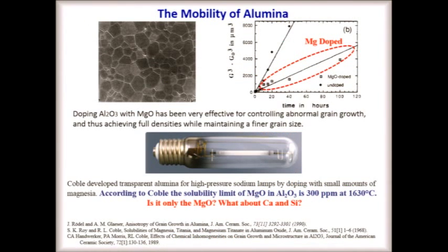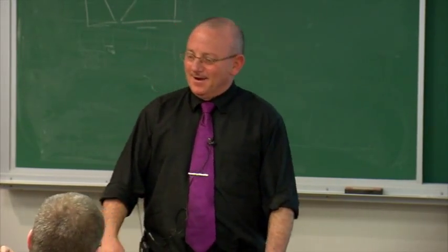All right, so alumina, which is my first love, we all know that certain dopants and impurities are important in alumina. We add magnesia to alumina in order to reach full density, remove pores or prevent them from becoming occluded by growing grains, detaching from the grain boundaries. They stay at the grain boundaries and vacancy diffusion makes it easier to eradicate them. But it also reduces grain growth. Actually, when I was a PhD student, somebody said that to me, and because I had always heard it was important for sintering, Arthur said, no, it's also important for grain growth. Don't you know that? And I remember that to this day.